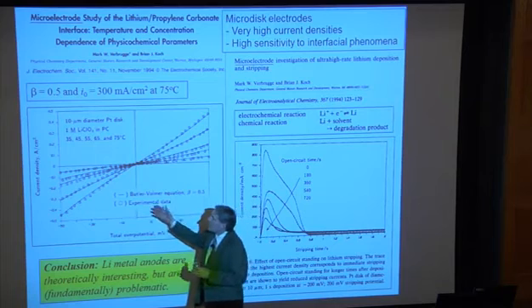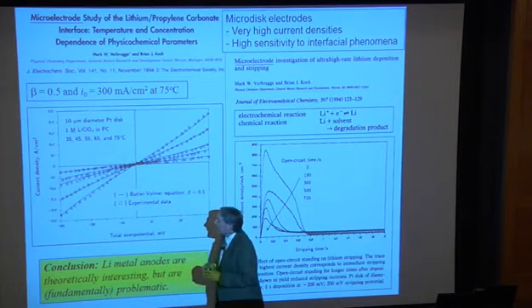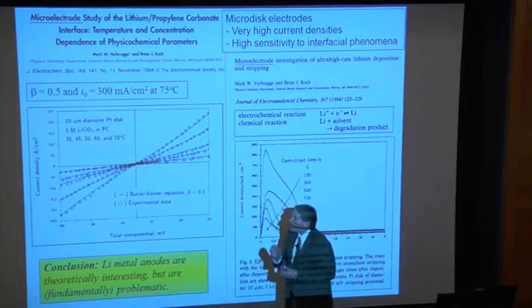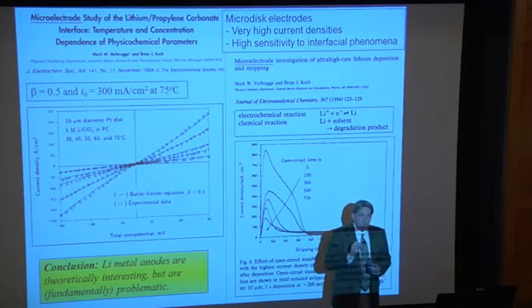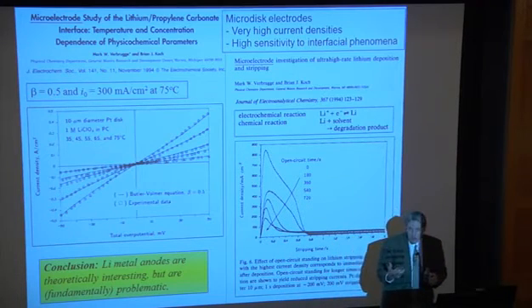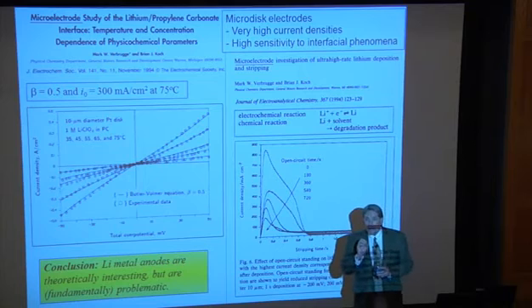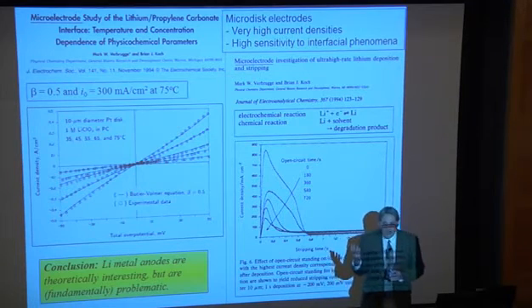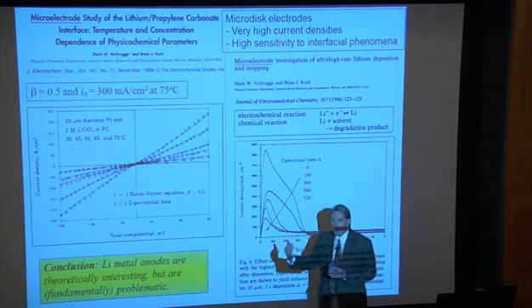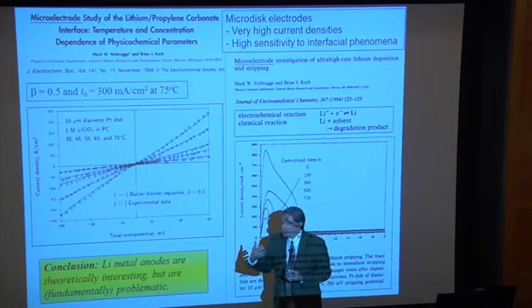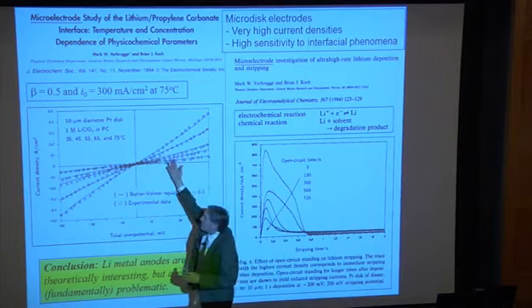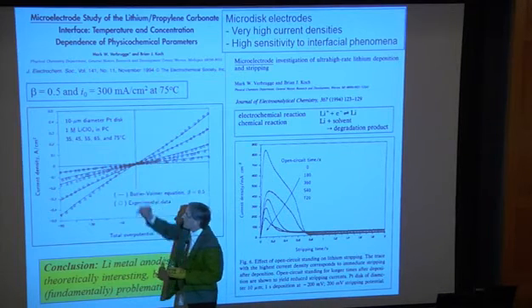But when you look at lithium itself, just the lithium reaction, what you find is that it's actually, as you'd expect by Marcus theory or by people who have looked at electron transfer reactions, a classic electron transfer reaction, and that it is extremely fast. Now, lithium is a very light element, obviously, and it has one electron transfer. It's well solvated, and so it has a perfect 0.5 symmetry factor. It's very symmetric to charge and discharge reactions.